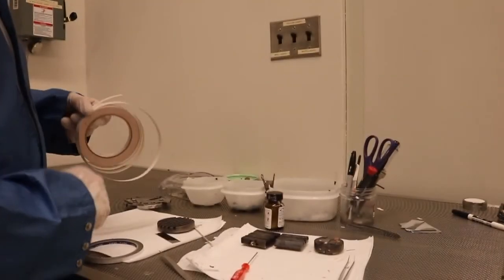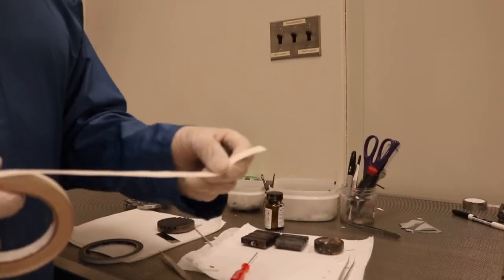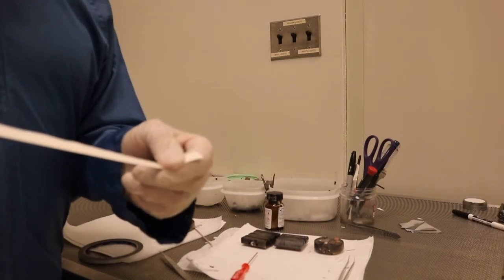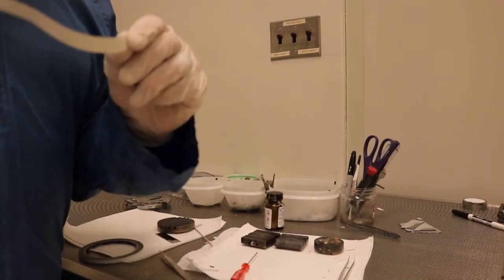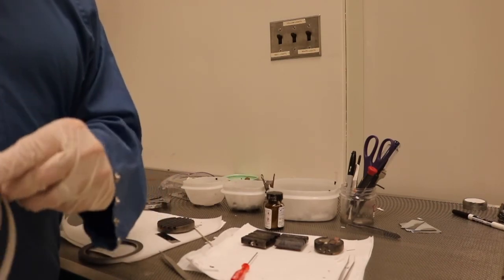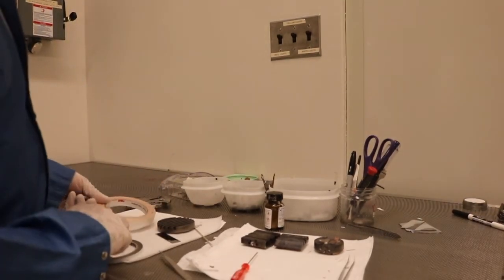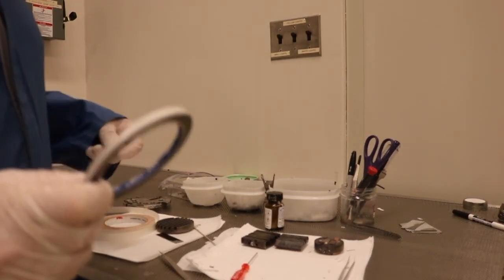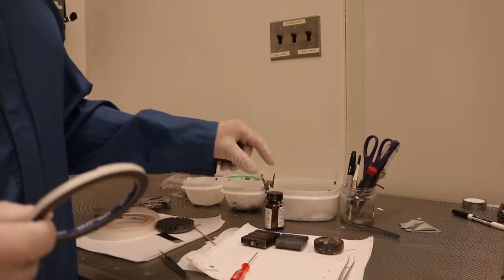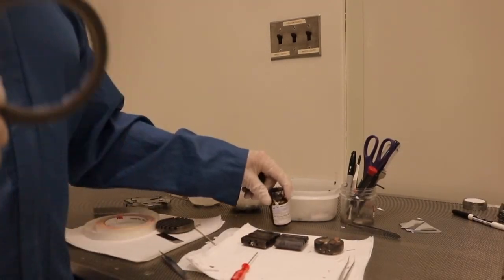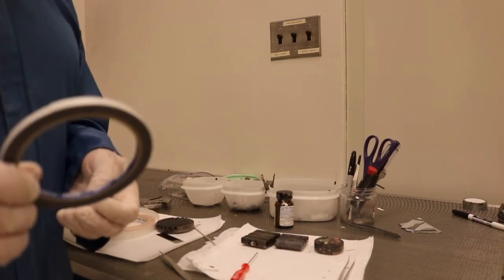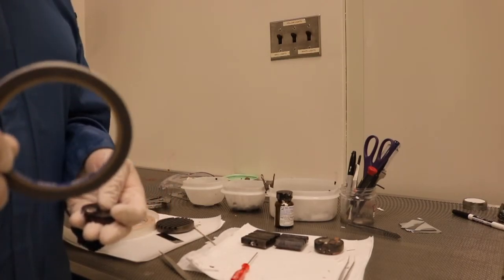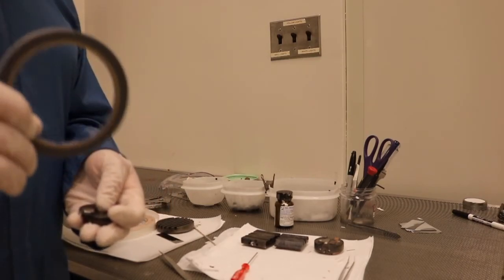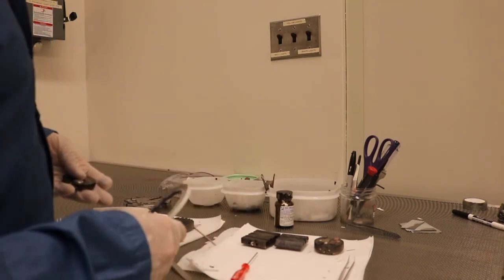The best choice for low residue would be the double stick copper tape. The only problem here is that the adhesive is not absolutely the most conductive thing in the world. Carbon tape is probably the next most conductive behind the silver paste. The only problem is this stuff is very, very sticky, and after it's been in the vacuum for a while, it is very, very difficult to get your samples off of this material.